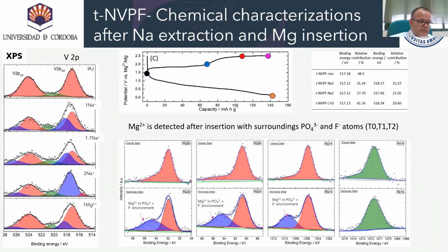On the left, we represent the vanadium 2p core levels. The original sample displays peaks typical of vanadium 3+. The charged electrode exhibits broadened peaks due to the presence of tetravalent vanadium. The extraction of a second electron involved a significant increase of the contribution of the pentavalent ions of vanadium, thus evidencing the electrochemical oxidation from vanadium 3 to vanadium 5. On discharge, the same electrode recovered the trivalent oxidation state with some traces of tetravalent state. This result confirmed the reversibility of the multi-electron reaction.